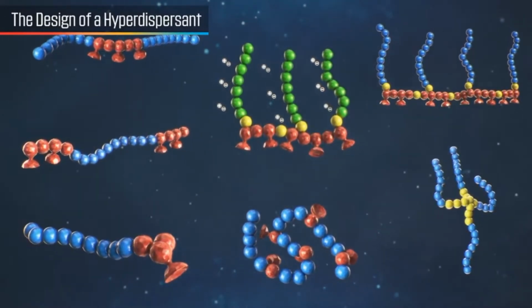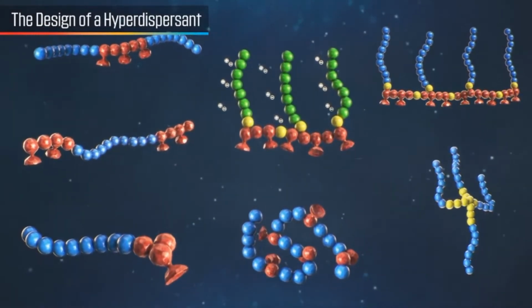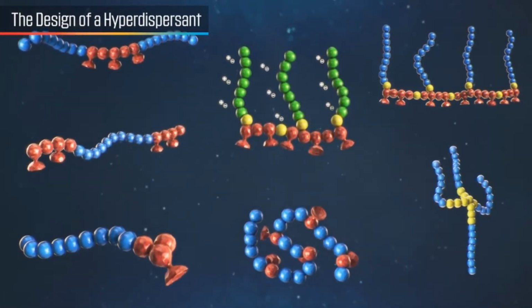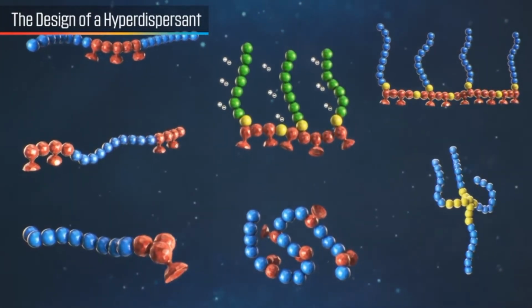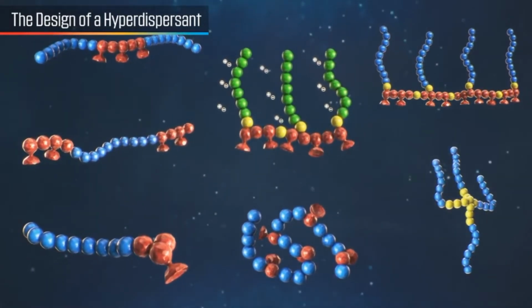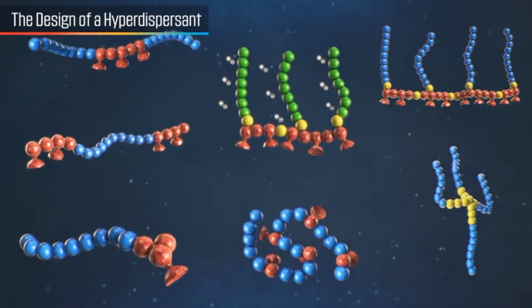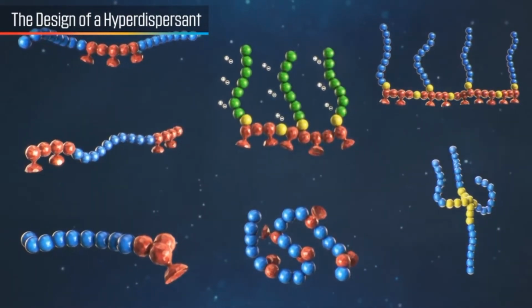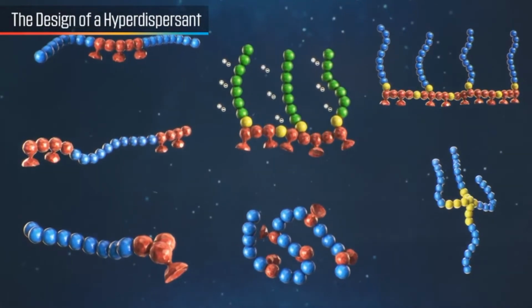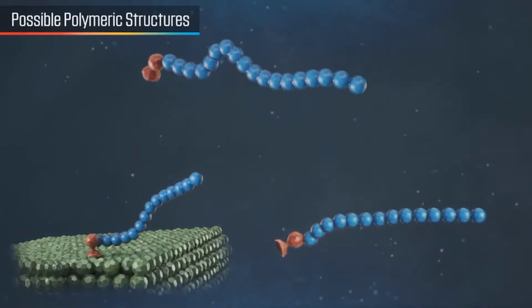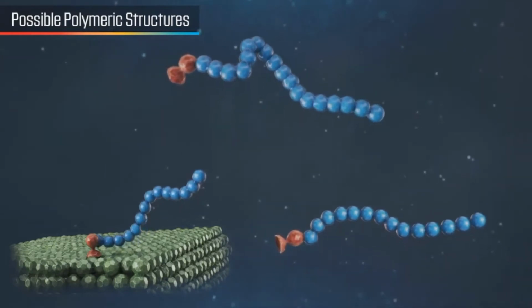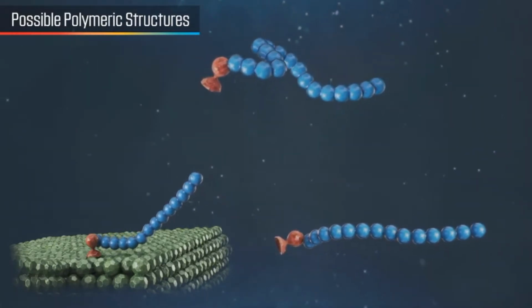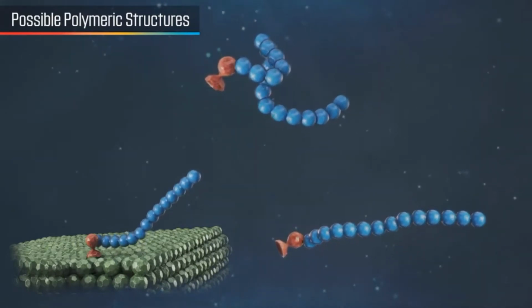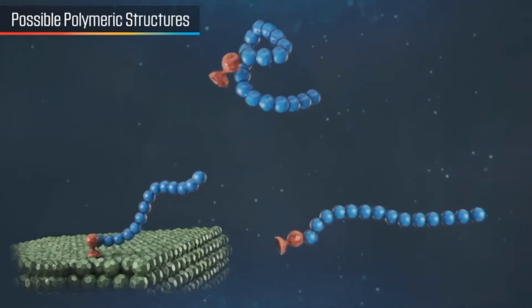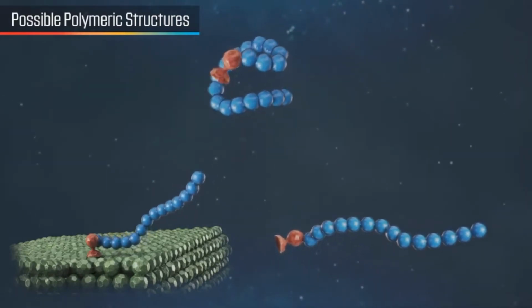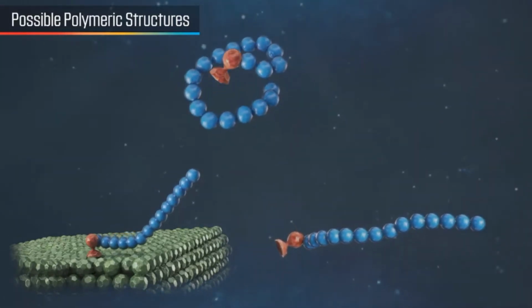Dispersants are two-component structures. The anchoring group provides strong adsorption onto the pigment surface. Polymeric chains, which are attached to the anchor group, provide the stabilization. It is the particular combination of the anchoring group and polymeric chains which leads to the effectiveness of hyperdispersants. Single anchor, single chain structures are polymers with terminal function groups. They are fast wetting and good with grind resins. Single anchor dispersants, by their nature, only contain one type of anchoring group. Therefore, they are most effective on a single class of pigments.